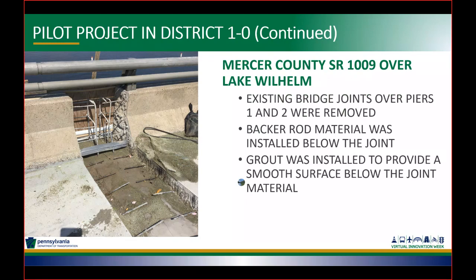Here's a close-up picture of what the removal looks like. Essentially, what you're doing is removing about a foot to a foot and a half on either side of the joint. You're only removing down about 4 to 4.5 inches in this case, but that also involves removing the parapet as well. The longitudinal rebar was saved and incorporated into the new link slab.